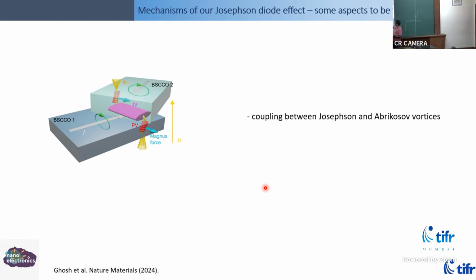But because of this material, if you apply a magnetic field and you twist them, what happens is that the two halves of the pancake vortices can get split up and you can get an in-plane Josephson vortex. And that is central to this. I'm going to wrap up in a couple of minutes, actually. And the fact that there is an in-plane Josephson vortex is central to this observation of this Josephson diode non-reciprocal response.